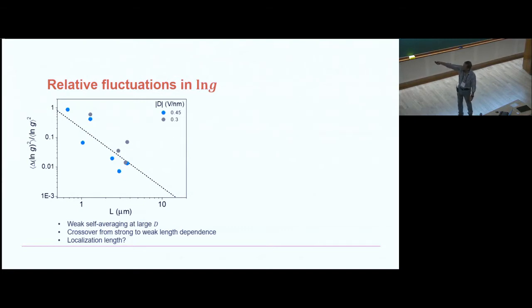So if you have a small band gap, so the transport is very strongly affected by the bulk of bilayer graphene, then the self-averaging is clear: the relative fluctuations come down. As you increase the length of the system, they come down very fast, and this goes as 1 over L squared, as it should in a bulk 2-dimensional system.